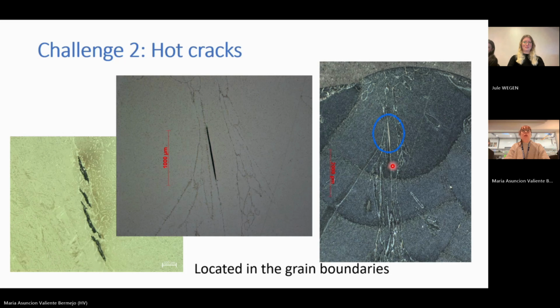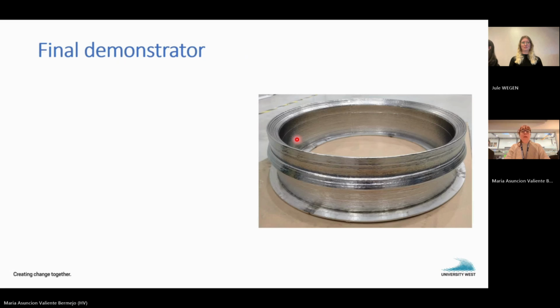And the amount of austenite in the boundaries was very little. Austenite, as I told you in the very beginning, is more ductile. And if we have very little austenite in the grain boundaries, then we can end up with these hot cracks, because there is no possibility for the microstructure to absorb all these stresses.